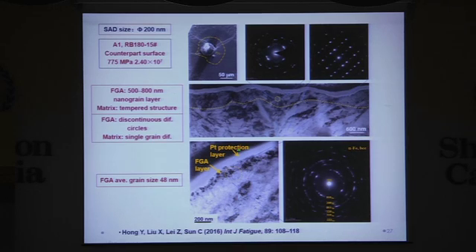And this is another result showing that in the region of the FGA area, the diffraction is a discontinuous circle, and our measurement shows that the average grain size is 48 nanometers.